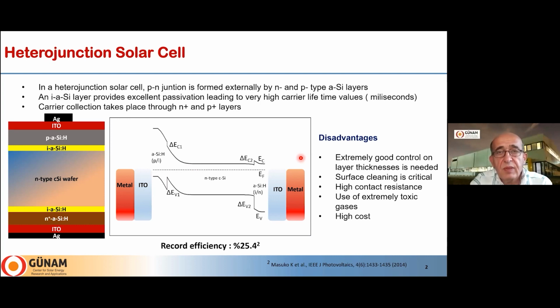But we have still some disadvantages. So you need extremely good control on the layer thicknesses. This intrinsic layer and also the amorphous doped layers should be controlled in a very well way. And then you need to have exactly the same thickness values in all different fabrication cycles. Surface cleaning is very critical for the passivation. For a good passivation with intrinsic amorphous silicon, you need very high cleaning, extremely pure surface. So another disadvantage is the contact resistance between silver, ITO, and the amorphous layer. So this needs to be also studied and solved carefully.